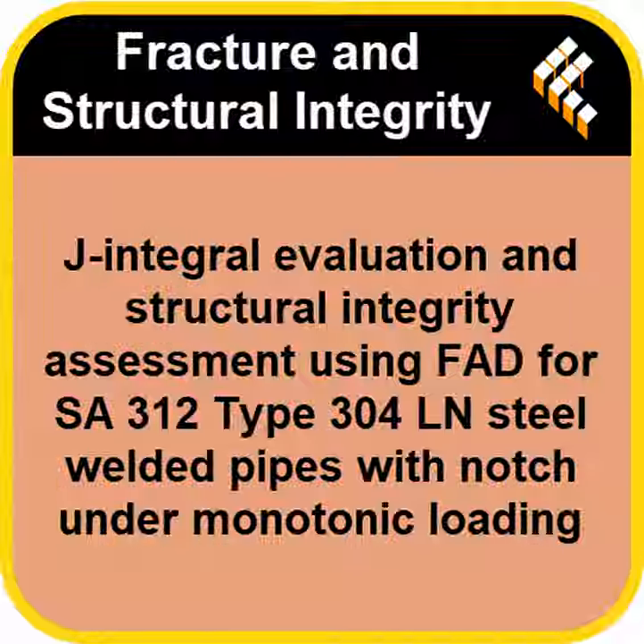Okay, so let's dig into that comparison. First, the limit load moment calculation, which determines LR, our capacity utilization ratio. They compared Zahoor's expression against Takahashi's expression. This is where a core conflict lies, right? Absolutely. The difference really boils down to how they define the material's effective strength under large deformation. Zahoor's expression incorporates the flow stress. Now, we need to be clear about what flow stress means. It's typically taken as the average of the material's yield stress and its ultimate tensile stress.